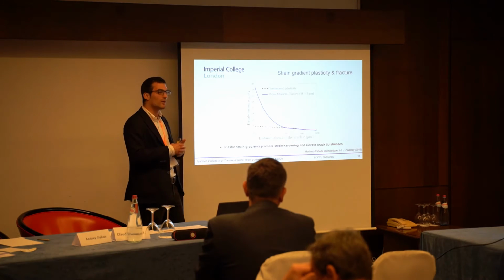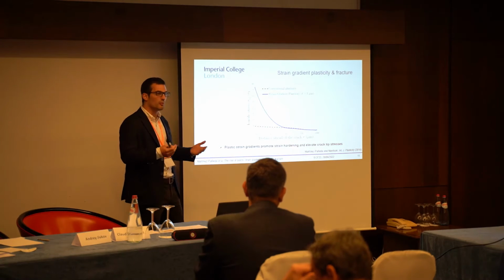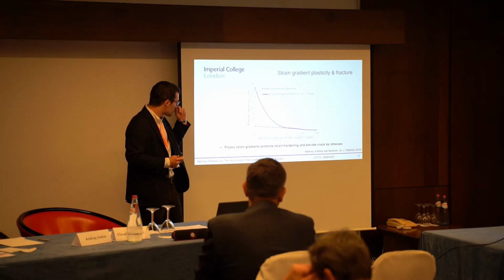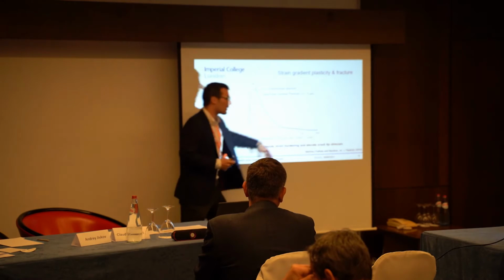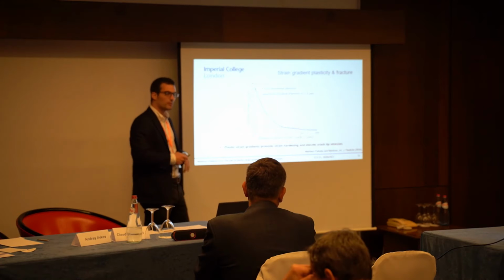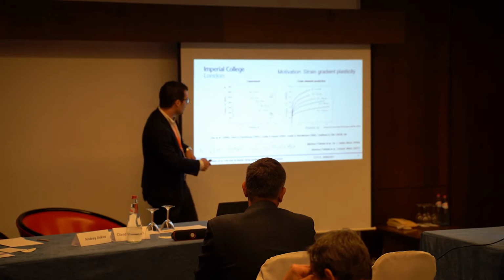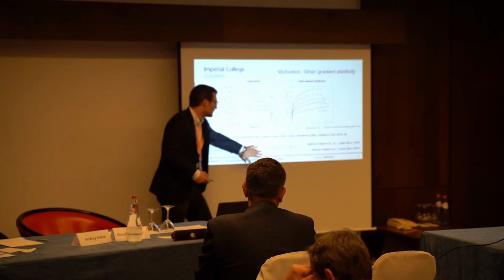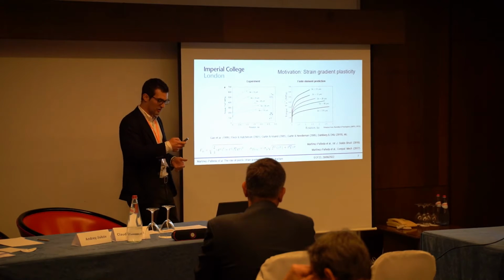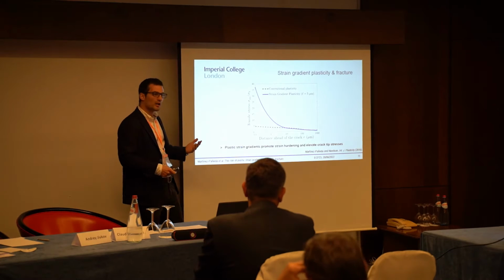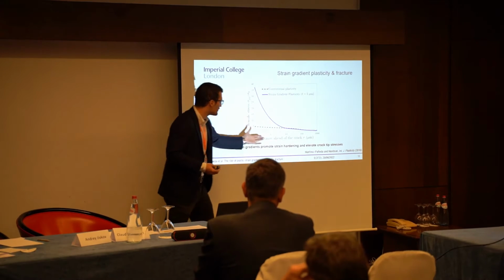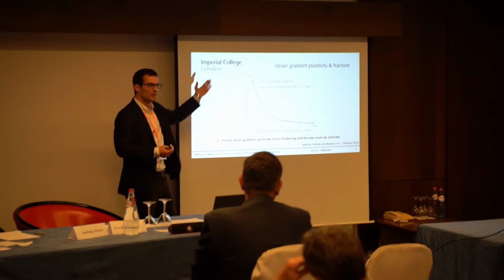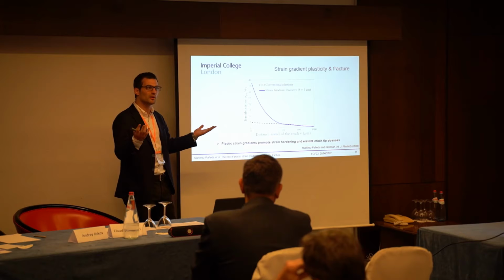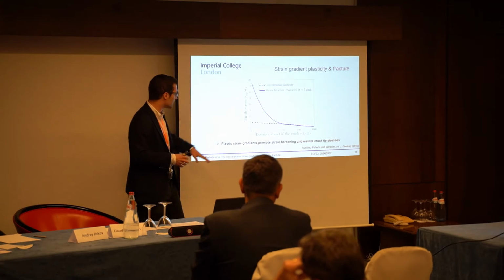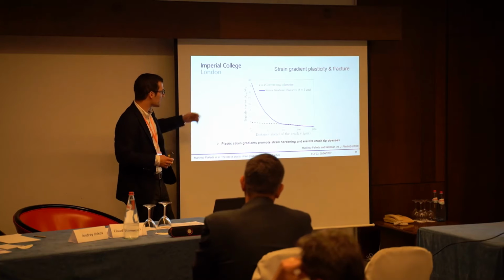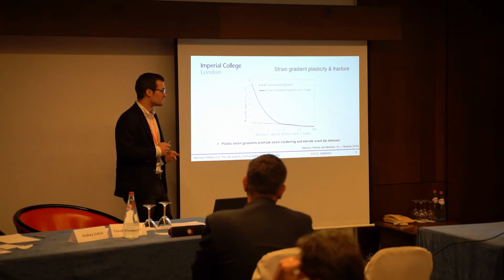So the first thing that we did was to take one of those strain gradient plasticity models and to simulate what were the crack tip stresses ahead of the crack. And the first thing that we saw is that far away from the crack tip, the stresses are the same as those that you predict with conventional plasticity, because, as you can see here, the moment your plastic zone is too large, then this term becomes negligible and you recover the predictions of conventional plasticity. But whenever you approach the crack tip, you have these big gradients of plastic strain, so you have these dislocation hardening effects that are elevating your stresses. So it seems that this could be an explanation for that conundrum that we have, understanding brittle fracture in the presence of plasticity. It seems that maybe one can get those stresses based on the fact that you have dislocation hardening mechanisms associated with plasticity.